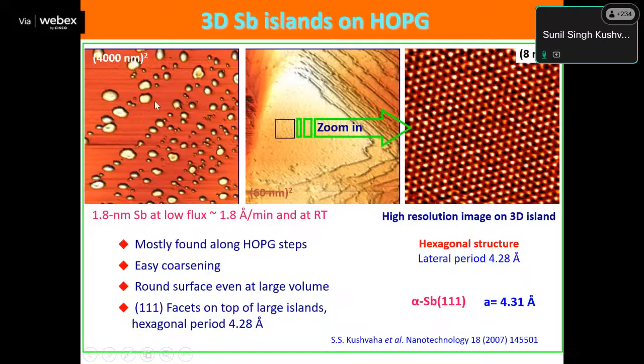Then you scan the large area, then you move to the 50 nanometer square area. You can see here on top of this one the flat surface. Even after zooming, you can scan at the 10 nanometer or 8 nanometer area, and from here you can see the crystalline structure. So it means even locally, from the STM, you can measure the step height. Also, you can measure the crystallite structures. And from here, you can also correlate whether it follows your substrate and your grown film or not. And even if not, whether it is epitaxial, or local epitaxial, or even the crystal structure at the nanoscale.